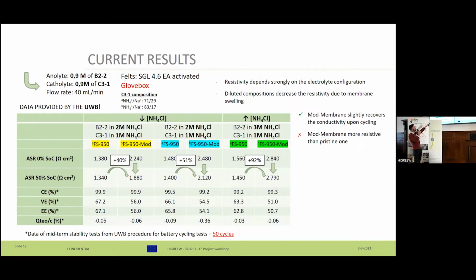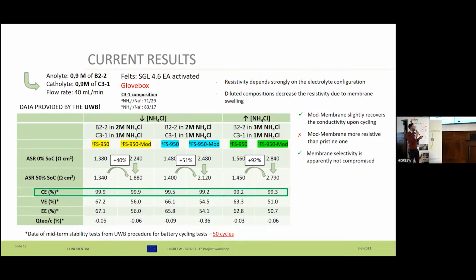For example, in the diluted cases, we have a near 40–50% increase in conductivity, whereas in the concentrated ones, we are dealing with near 90%. So this fact reinforces what I have aforementioned. And also, having a look at the Coulombic efficiency, our modified membrane apparently does not compromise the perm-selectivity. So the exchange of ions will be done as with the pristine ones.